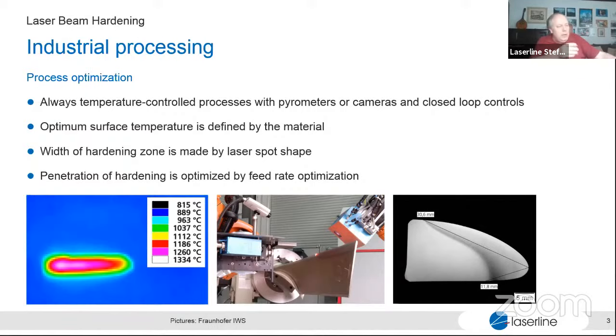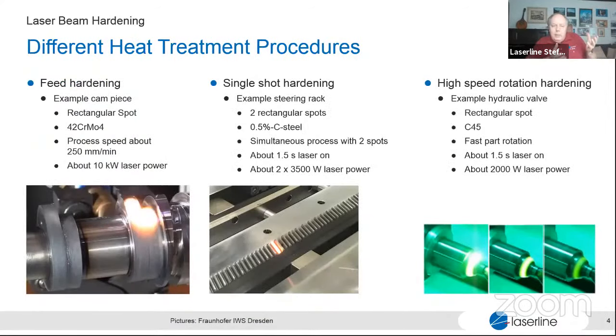Sometimes we need a rectangular spot, but in most cases we need some flexible adapted spot in size and intensity profile. And that depends a little bit on the processes. Sometimes we have processes, you see the center, where a rectangular spot is sufficient. We apply two rectangular spots to harden a tooth of a tooth rail, shot by shot, tooth by tooth, two simultaneously applied spots. And the customer has different sizes of his rails, so we need just a rectangular spot, changing in size.